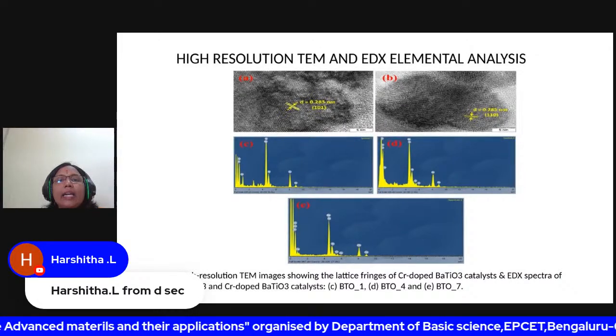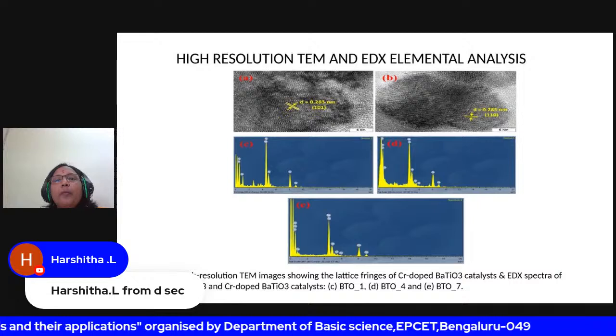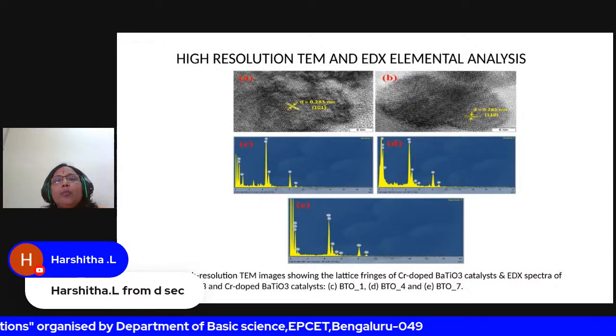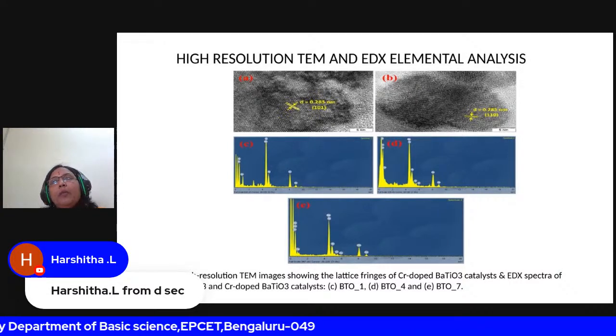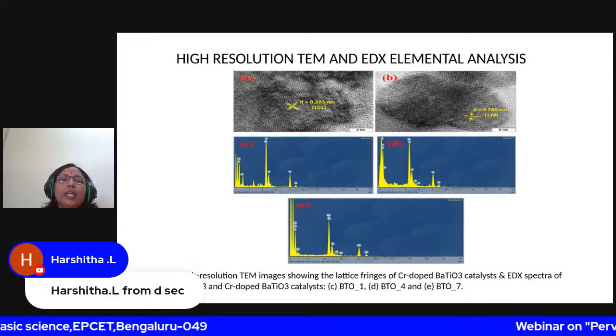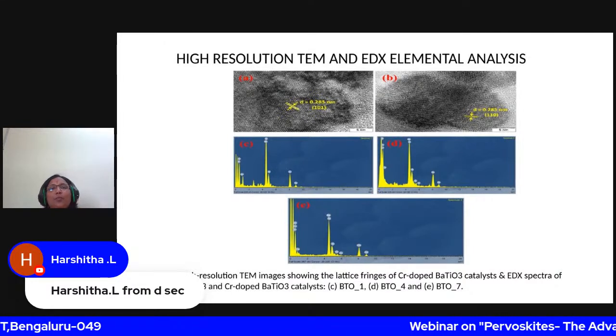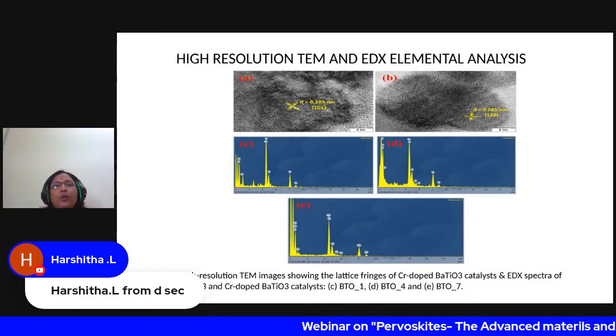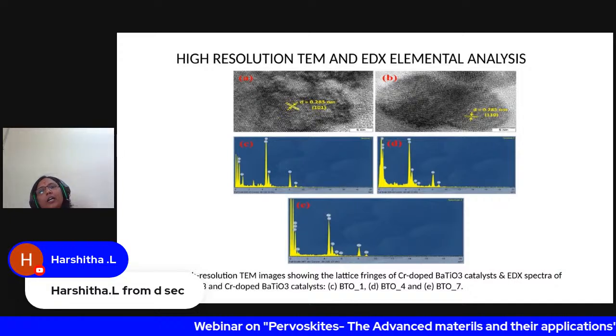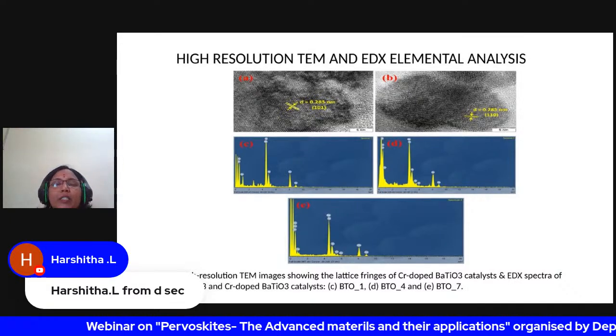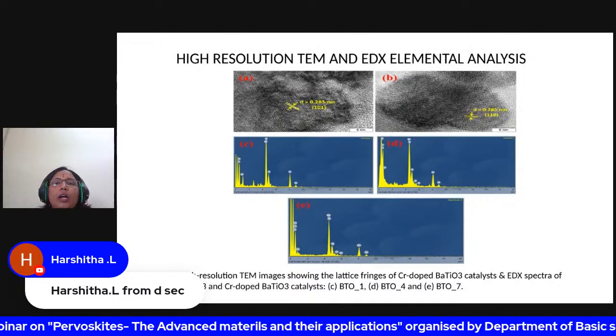And the EDAX analysis reveals the presence of barium, titanium, oxygen, and chromium in the samples. So here you can see clearly, because these are very small images, if we zoom in, we can see clearly. So we further confirm that chromium is doped in place of titanium.